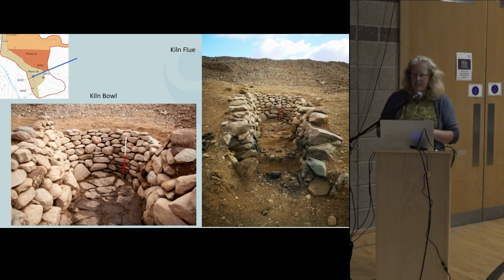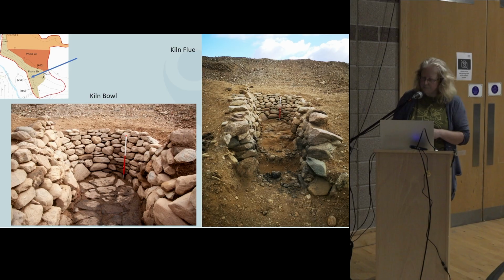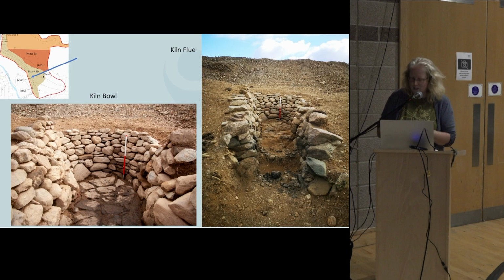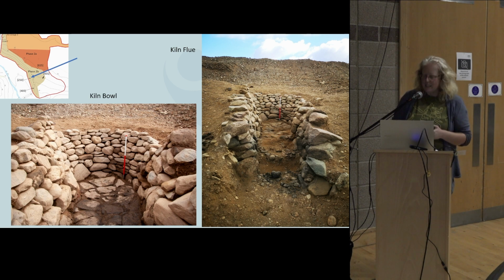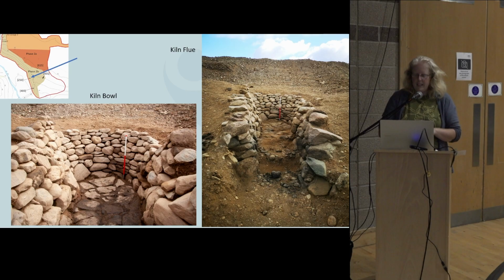It was confirmed to be a kiln feature rather than a souterrain, which was one of the early interpretations of the features, and this was in part due to the bowl-shaped nature of the terminal, which you can see on the left-hand image. The stones also widened towards the top of the flue rather than narrowing in, meaning corbelling would not have been possible. If you combine that with the substantial grain assemblage, hence the Grain of Truth title, that was identified during the post-excavation programme, and the multiple fragments of Scottish medieval redware pottery in the infill, this confirms the interpretation of these features as substantial grain drying kilns dating to the medieval period.